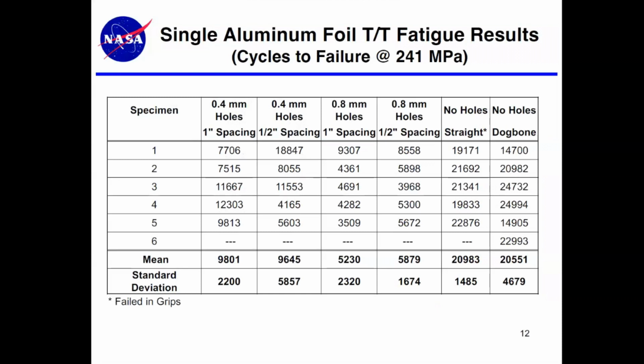We did a little bit of testing. I have to admit that most of this work was done without a great deal of programmatic support. So we're kind of on a shoestring budget. Most of our work was trying to develop the experiments that would allow us to patent the process, and we weren't able to spend a lot of time generating mechanical property data. But the one thing we did was want to understand the damage caused by the holes in the aluminum foil. So this is some specimens we tested on fatigue resistance, cycles to failure of different foils with different size holes and spacing.